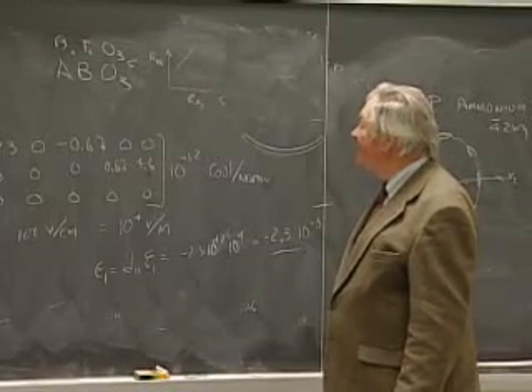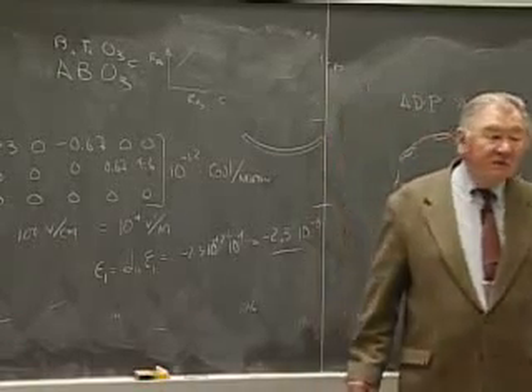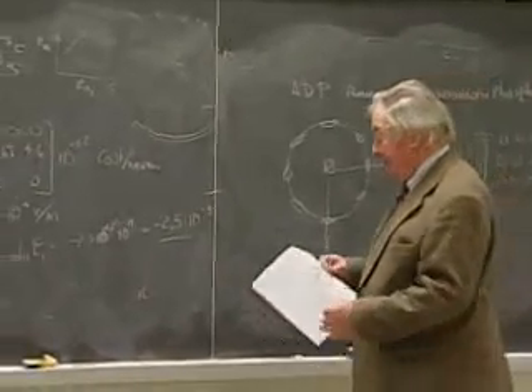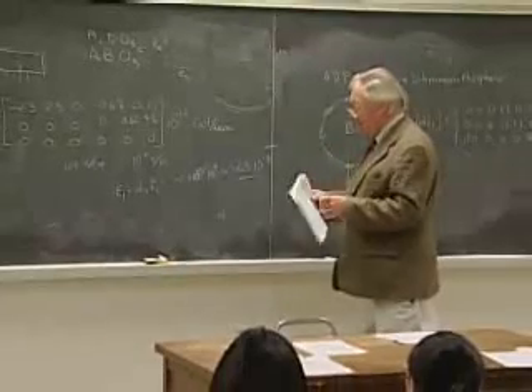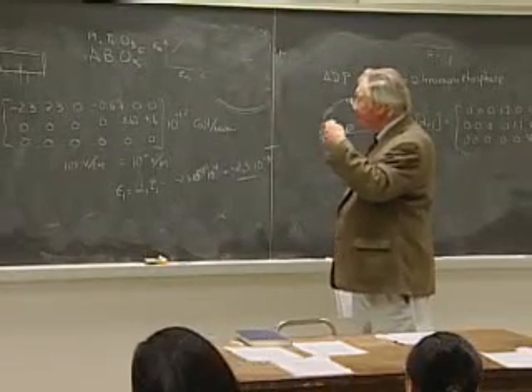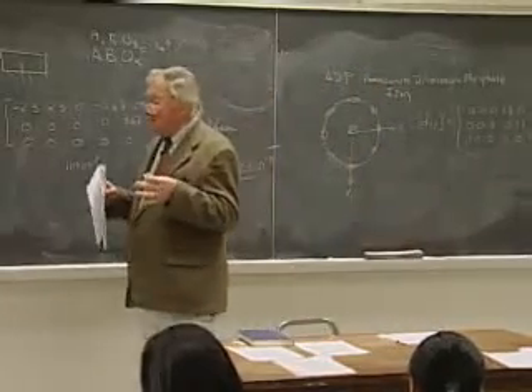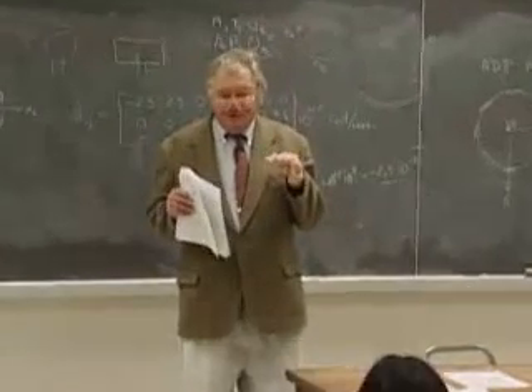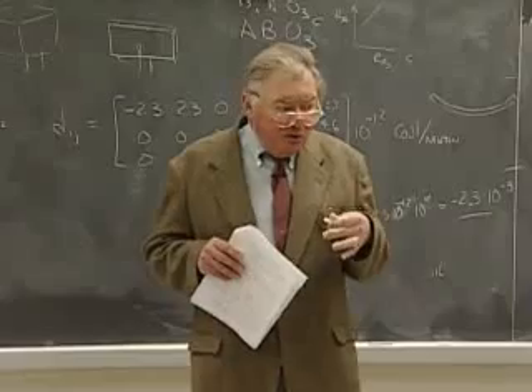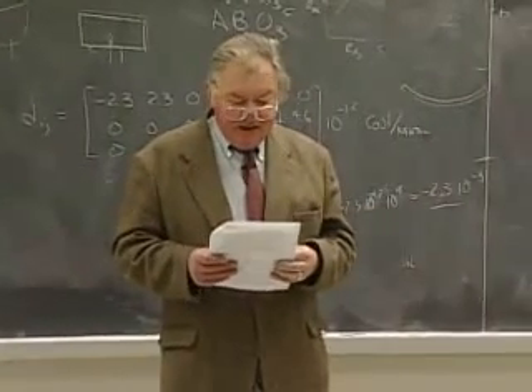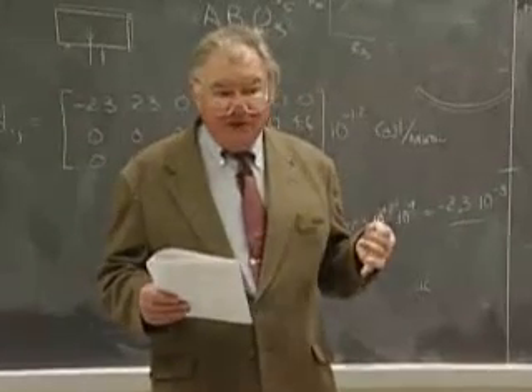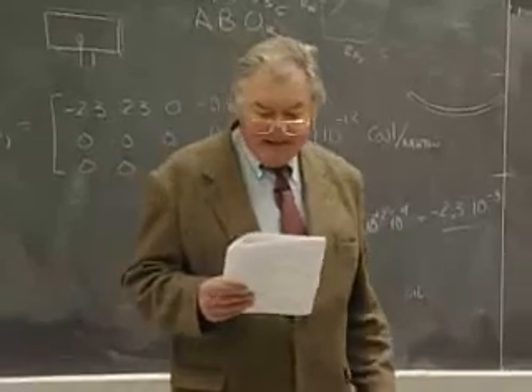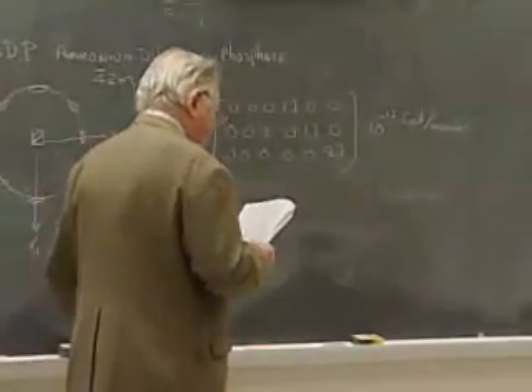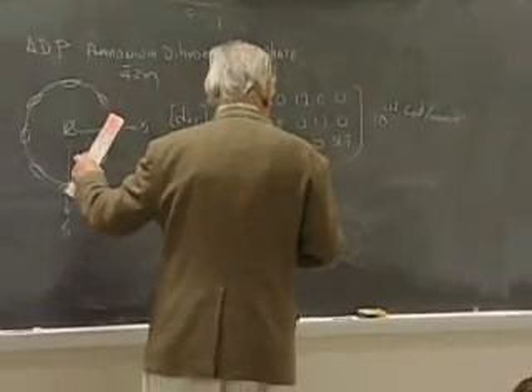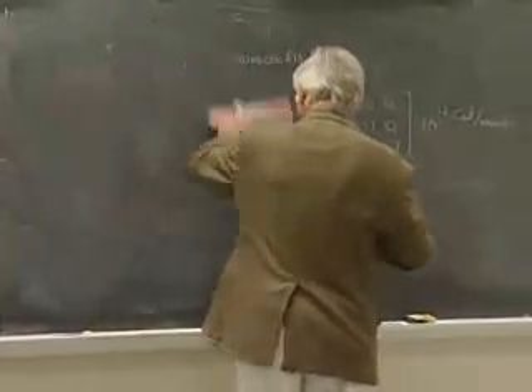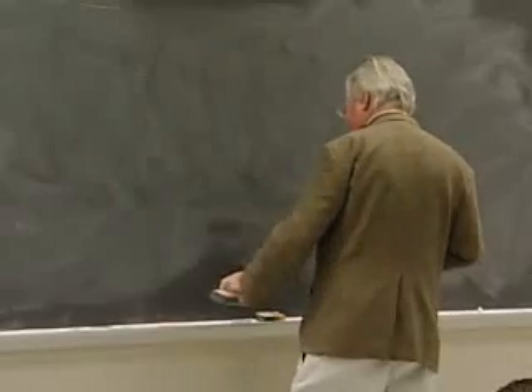Okay, in order to do that, many of them distort to tetragonal forms, others distort to superstructures which have very, very large unit cells. But in any case, when you're right at the phase boundary between the distorted structure and the true perovskite structure, these materials sometimes have very, very complicated solutions of the two phases on a very fine scale. And it's not known exactly why they have this property, but they have absolutely enormous piezoelectric moduli very close to this phase boundary. And the reference that I give you here is a compound that is a lead titanium zinc niobate. And the complicated composition is to get you close to this phase boundary.